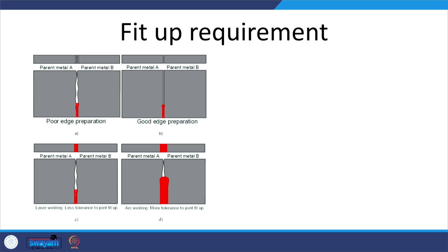So, what are the benefits that are realized? Say a laser offers heat delivery over a smaller area, but arc offers heat delivery over a larger area. When the heat delivery is over a smaller area, like in laser welding or electron beam welding, we need to have very good fit up, otherwise the beam will pass through the gap between the sheets. If the sheets are rough like this, and the edge preparation is not good, then the heat source will pass through the gap between the two sheets being joined. So, we need very good edge preparation in order to ensure that the beam supplies the desired heat to both the sheets and parent metals for realizing the melting.